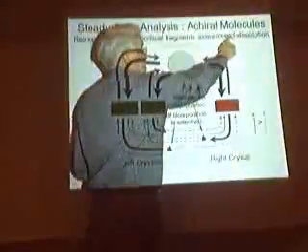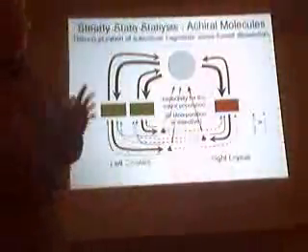So I'll pause just a minute if you want to convince yourself that that must be true. If more of these can be reincorporated because of the cross, the green ones, but not available here, then the reincorporation of subcritical fragments slows this forced dissolution. This is forced because it only happens because you're knocking off small pieces. And you'll slow that down more for the green than for the red. So now this dissolution is faster than either of these. Not faster than their sum, but faster than either one. Okay? The green crystals dissolve more slowly than the red ones if you include that they could be reincorporated selectively.